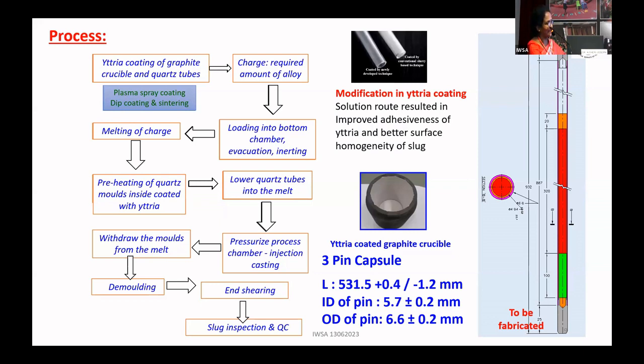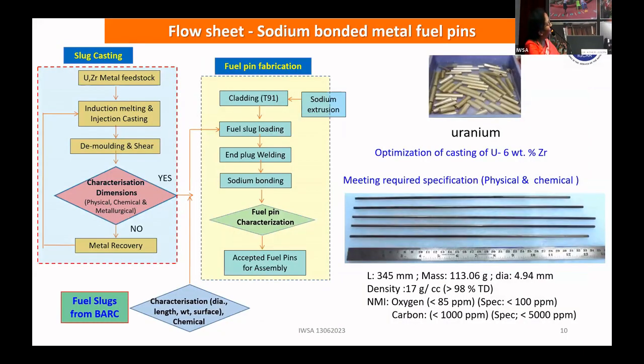The moment you are getting the slug, you have to go for quality check. What are the things? You have metal feed, induction melting, demolding, characterization. You should have physical, chemical, as well as metallurgical. The moment it is not qualified, you recover the metal and do the casting. If it is qualified, put it in T91 clad tube, sodium extrusion, slug loading, end-plug welding, sodium bonding. The fuel pin is characterized again. Accepted fuel pin goes for assembly. As you all know, I have shown the cleaned uranium here. The slug which is cast, the uranium zirconium slug, is also shown here.